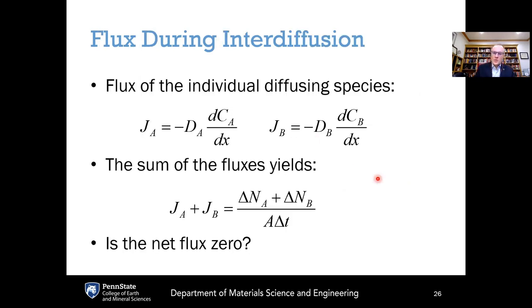And the key question with interdiffusion is: is the net flux of the diffusing species equal to zero? If yes, what that means is that the two different species are basically just swapping positions with each other. So for the flux of the individual species, if we've got particle type A, JA would be equal to, using Fick's first law, minus the diffusion coefficient of A times the concentration profile of A. For the second species B, the flux of that species is equal to minus the diffusion coefficient of B times the concentration profile of that species B.